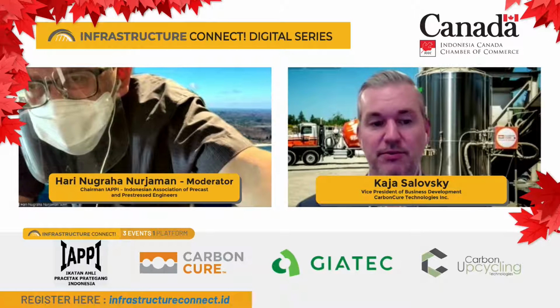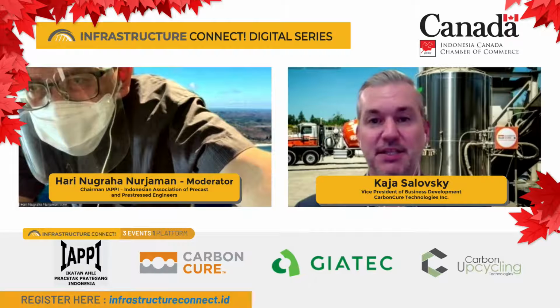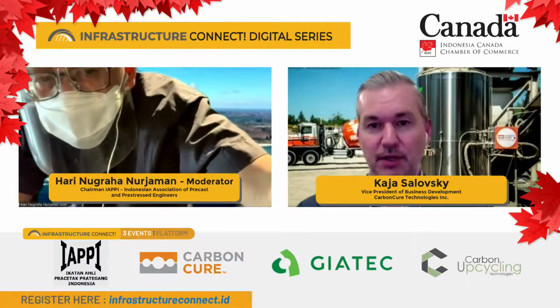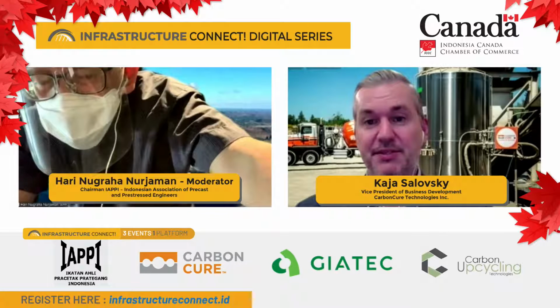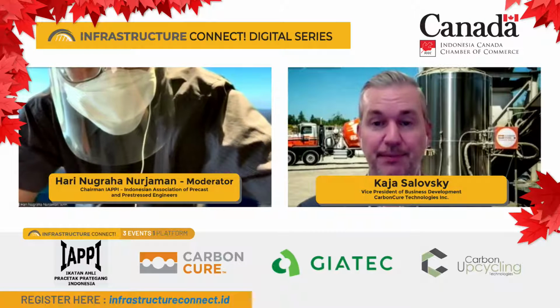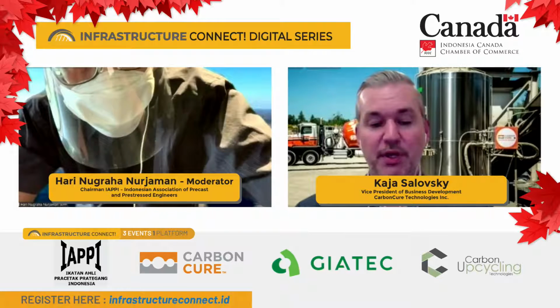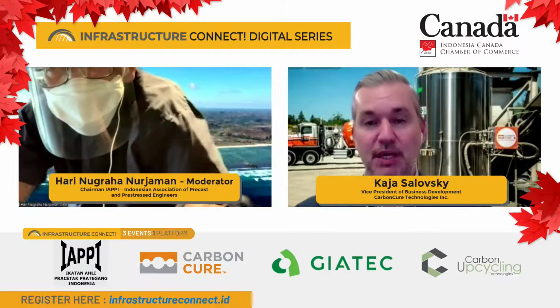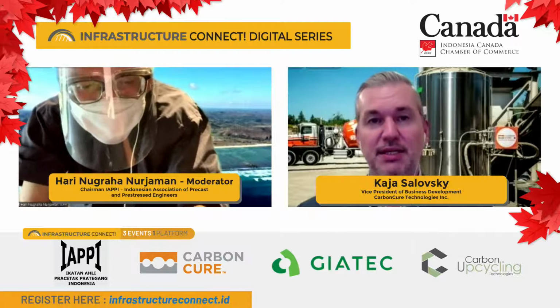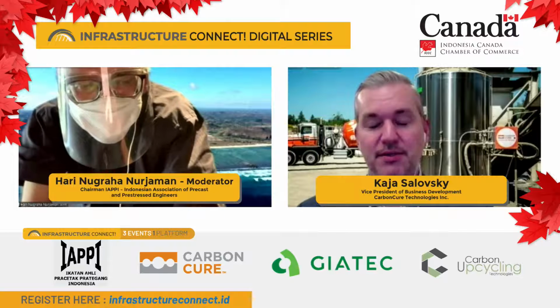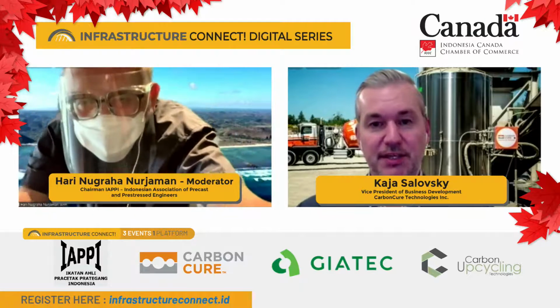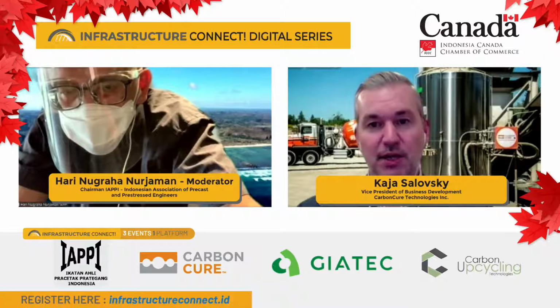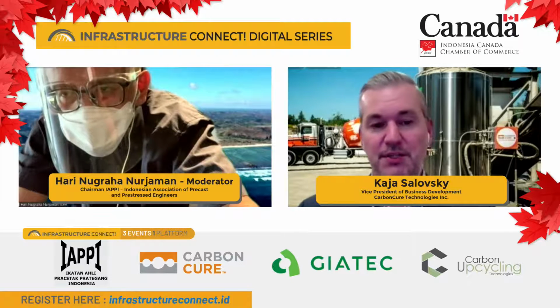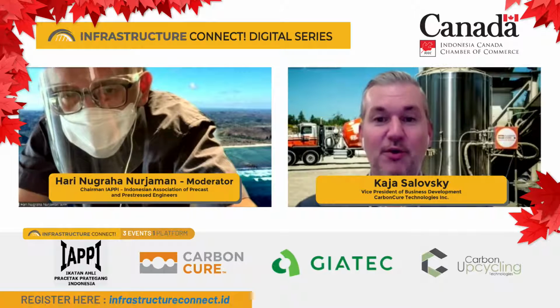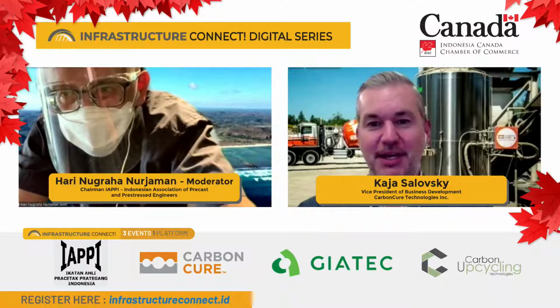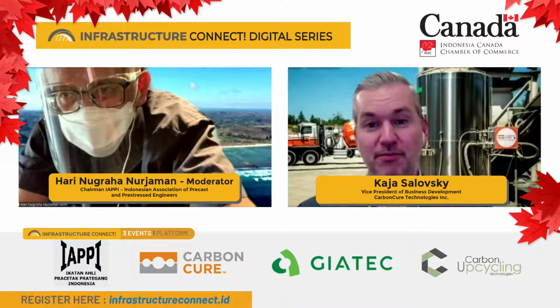You can only see them with a scanning electron microscope. So if you think of it this way, the science around seeding concrete with small particles to deliver improved strength is well understood. That's one of the bases of the use of waste products like silica fume, for example, as a densifier or as a strength improver. So what we have proven, and we have many white papers and studies to show this chemistry occurring, is that this fine precipitated calcium carbonate, those 400 nanometer sized particles, are the ones that are causing that seeding effect. The early sites of hydration are directly linked to those particles. And when you take early strength testing, whether it's at day 3 or day 7, we're seeing somewhere between 10 to 15% improvement in compressive strength. So back to the question, the type of calcium carbonate that you're adding in your cement blend is a much, much larger particle than the one that we're making in the mixer.